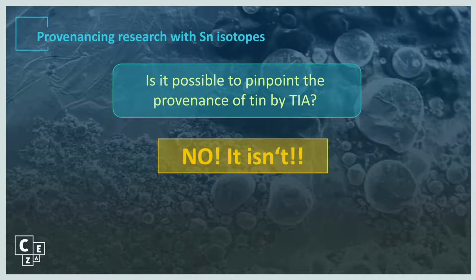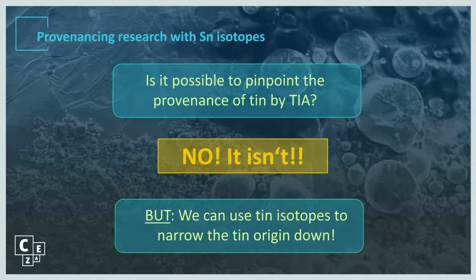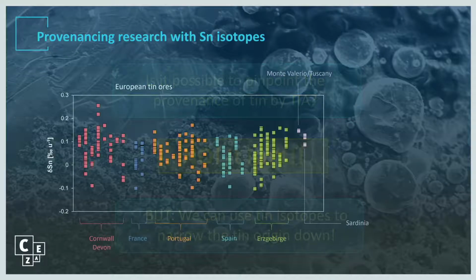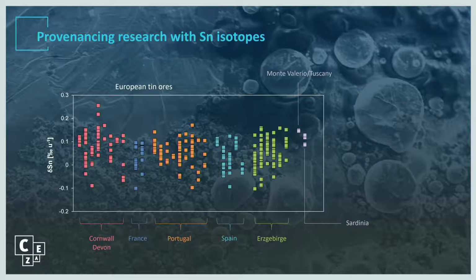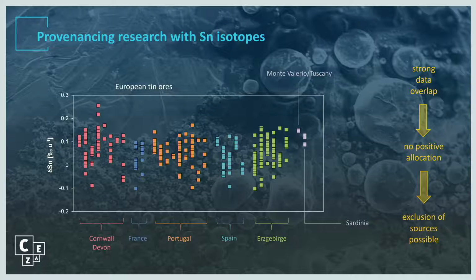So this sounds like a very frustrating result after such a long-lasting project. But besides this big no, there's also a big but. We can still use tin isotopes for narrowing down the tin origin. And here in the next slide, I show you tin isotope data of European tin ores. What we see clearly in this diagram is a strong data overlap between the different tin provinces that we analyzed, or from which we have analyzed cassiterites. So there cannot be positive allocation of the tin isotope composition to a potential ore. But as I said, we can use the data for the exclusion of possible sources.